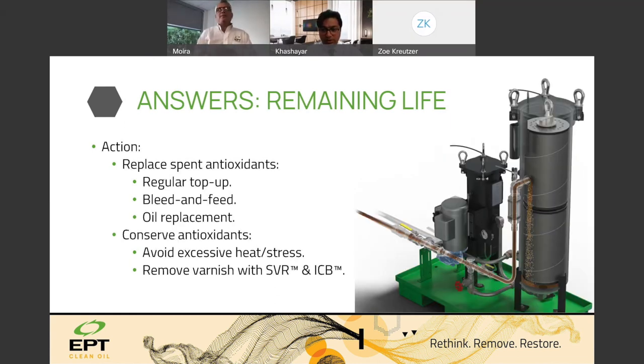One of the benefits of applying ion exchange resin technology to lubricants is that when you remove the oxidation material and you manage oxidation effectively, the rate at which lubricant additives are consumed will greatly decrease. Okay, so instead of losing 15% of your additive per year, we could get that into a highly managed condition of less than 5% per year, which would translate to a 20-year oil life normally.